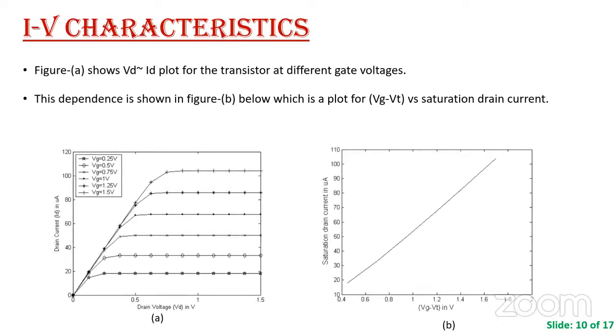So from figure 1, we can see that the plot is between the drain current and drain voltage, which is similar to the MOSFET, in which we have different gate voltages from 0.25 to 1.5 volts. We can plot the other graph between saturation drain current and Vg minus Vt, which is straight, linear, and it shows that the spacing between two consecutive curves is almost the same, which means that the saturation current shows a linear dependency with Vg minus Vt,